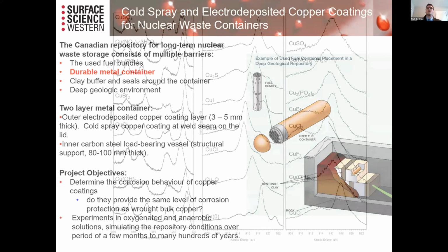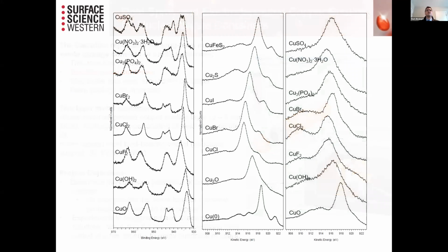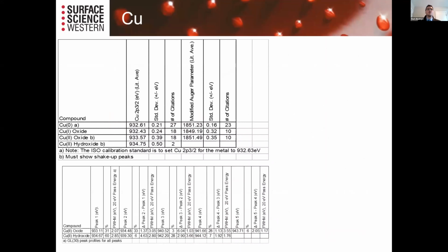And you can see this is a survey of different copper species. You can see that in the copper 2p spectra, we have all sorts of different shapes and positioning of the copper 2p and shakeup structure, for these are our copper 2 species. If we look at the Auger peaks, the LMM Auger peaks, we can also see that we have different binding energies or kinetic energies and shapes for the different species that are present. So we're going to use that kind of information. And so with copper, we do a whole bunch of different things where we look at the binding energies of the main peak. We look at what's called the modified Auger parameter, which is an addition of the copper 2p peak and the kinetic energy of the Auger peak. And that can tell us information about what's present.